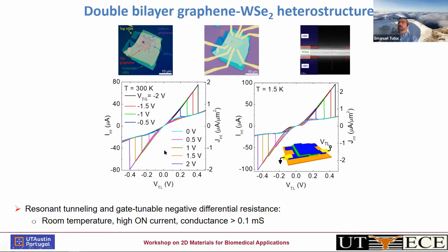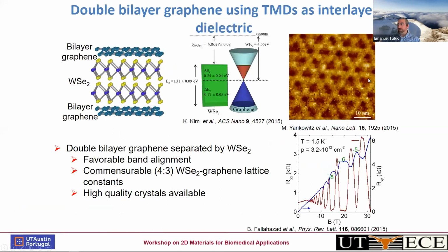And what you see here, when we measure the interlayer tunneling characteristic, you see this very sharp negative differential resistance that stems again from the energy and momentum conservation of electrons tunneling from one layer to another. If the layers were not rotationally aligned, this would not be possible, but rotational alignment enables this resonant tunneling.